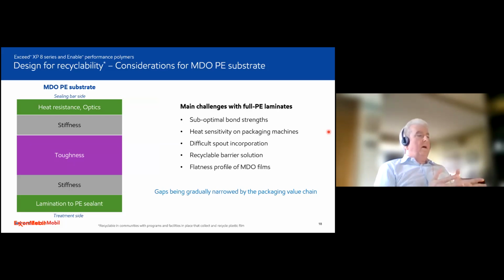So I'll talk a little bit about recycle and a little bit about barrier in another slide. This diagram I have on the right is a simplified 5-layer structure for an MDO substrate. And rather than listing the resins, I've listed the attributes that one may try to achieve when they make the substrate. Now, this is obviously the film that they make on the blown film line prior to the MDO. So heat resistance and optics, how do you do that? MDO is very useful there because you can afford to use a higher density type of polyethylene product when you've got MDO and not sacrifice your optics, and also get good stiffness. You'll probably still need extra stiffness on some subskin layers, and you still need a degree of toughness in your substrate, but obviously toughness normally means bringing down the stiffness. So again, the MDO compensates for that to a large degree.